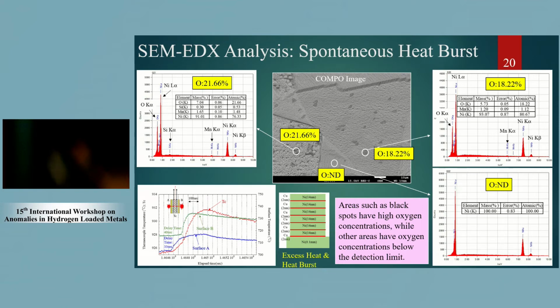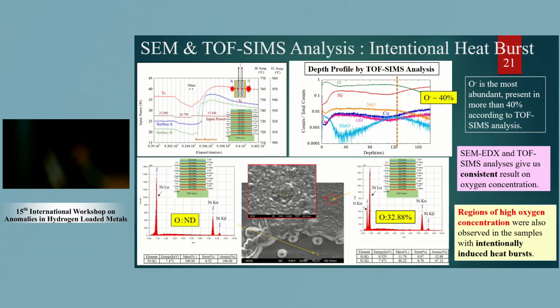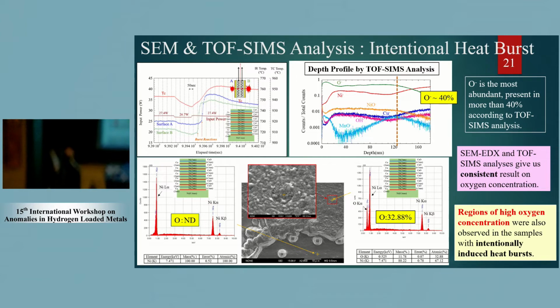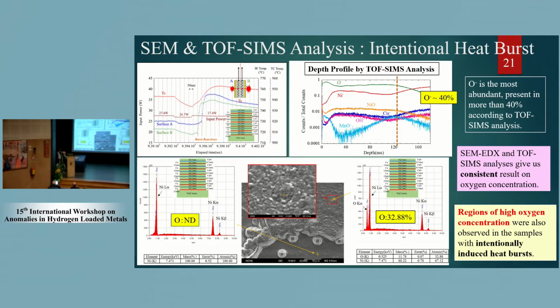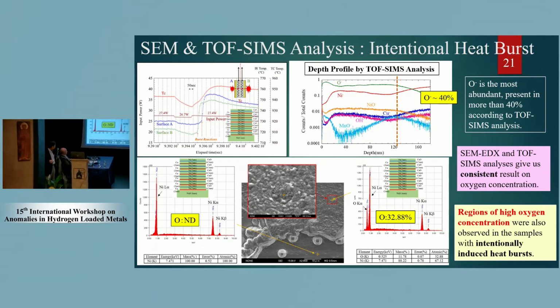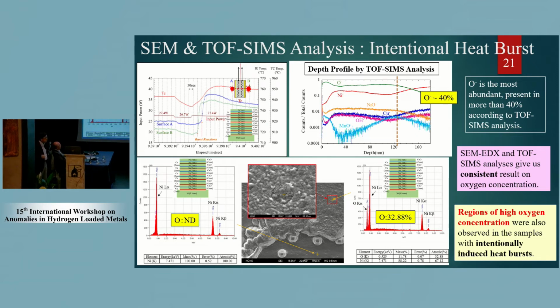This is SEM-EDX analysis for spontaneous heat bursts. I introduced these 2 spontaneous heat bursts that occurred. In this case, we can also observe dotted points like this. At the dotted point, we can see very large oxygen concentration here, but at a normal point, we cannot see any oxygen. Areas such as black spots have very high concentration, while the others have no oxygen concentration, okay? And this is analysis for an intentional heat burst sample, this one. We also see a black point here, and at this point it's 32.88%, a very high concentration, but at the normal point, no oxygen here.